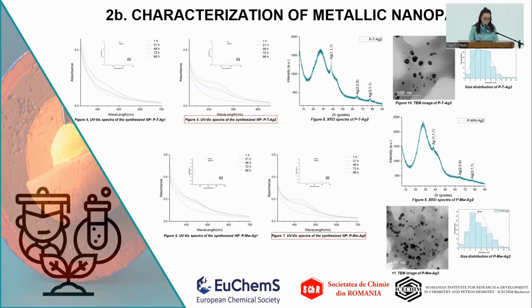The UV-Vis spectra of the samples show the appearance of the specific silver nanoparticles absorption peaks in all cases of synthesis protocols. The nanoparticles photosynthesized in a 1:2 ratio exhibited a better defined absorption maximum for silver, and the peaks tend to shift towards shorter wavelengths, indicating a hypsochromic effect. So the UV-Vis spectroscopy confirmed the formation of the nanoparticles in all the synthesis protocols, and in a relatively short time of 96 hours.